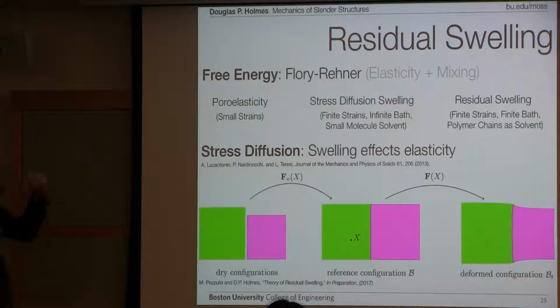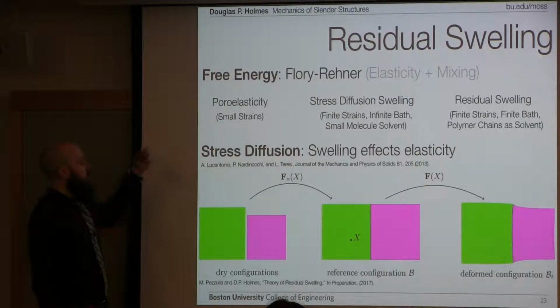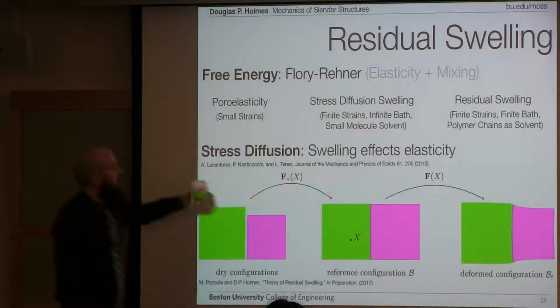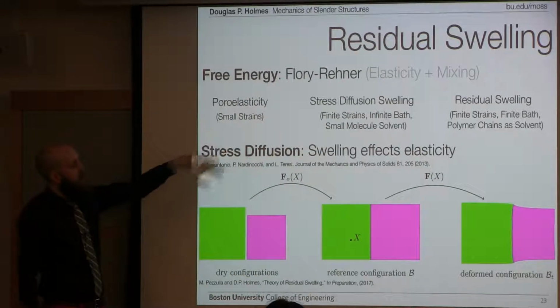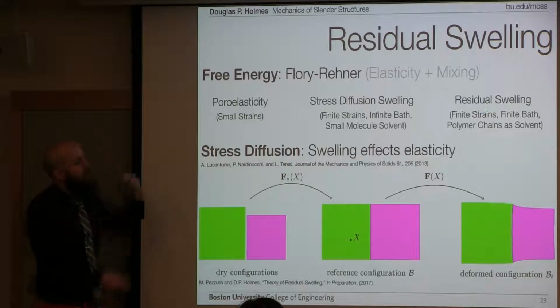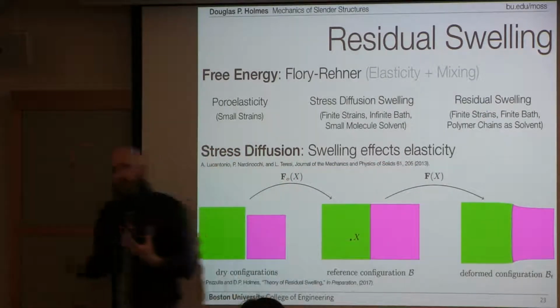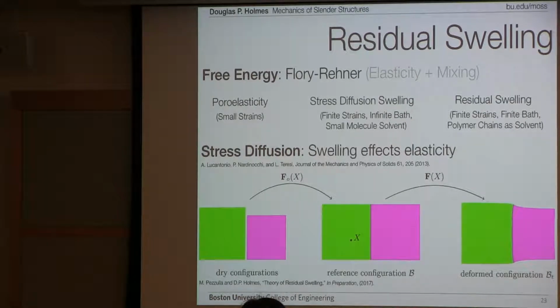So we can use this to develop a theory of residual swelling, in which the difference between here and here is that in these larger strains, considering the polymer chain as the solvent, the swelling changes the elasticity of your structure. And that's important, and that's what makes the problem hard.